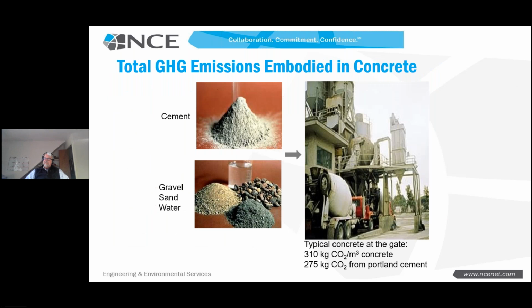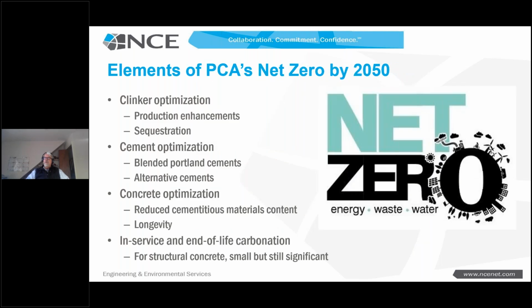So we take that cement, we mix it with gravel, sand, water, obviously some admixtures, and for a typical concrete at the gate in the US, we have about 310 kilograms of CO2 per cubic meter. 275 of that is from Portland cement production. So when you look at those numbers, you know where the focus needs to be, and that focus needs to be on Portland cement and what we can do.